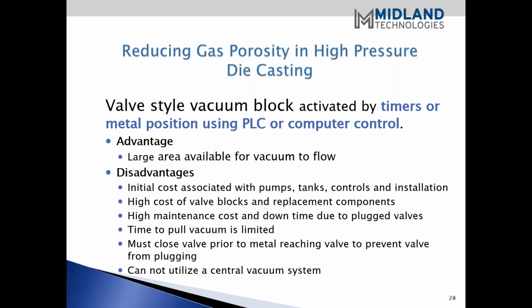The time to pull vacuum is limited. The valve must close prior to the metal reaching the valve to prevent the valve from plugging. So there is a timing issue, and it can affect whether you're able to evacuate enough air out of your die. And also these systems are typically a single unit, and they can't be used in a central vacuum system.